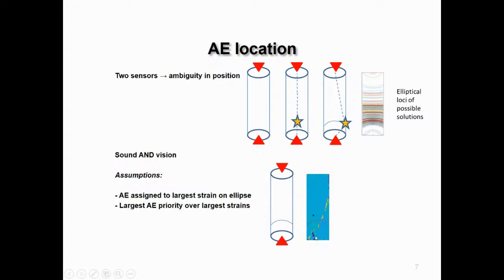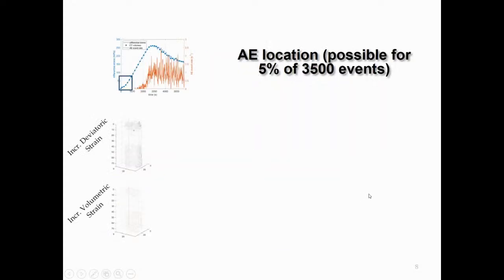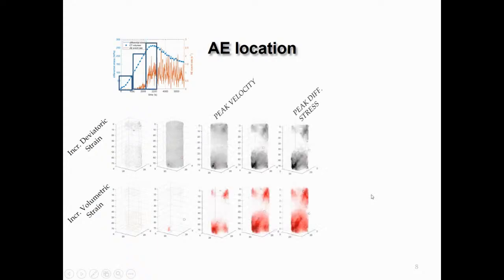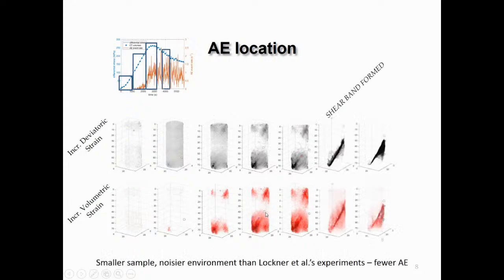So we use the strain field as a prior, a strong prior. So we put the event there. And so you can see there's few events, and then you start to get more, these red dots. Some of them are on the shear plane, and some are still off it. There's quite a few big events off the shear band, which I'll come to later. You begin to see some localization here of the acoustic emissions.